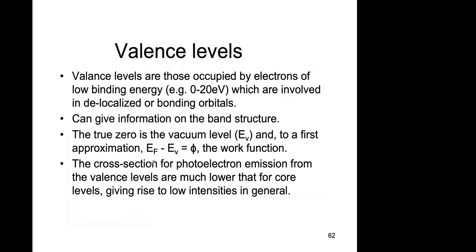So this is sort of valence band level. They have very small binding energy, and I showed you that previously, that it's really almost at the Fermi level. So it's from 0 to 20 electron volts binding energy. That's called the valence band region. And this can give you a structure.